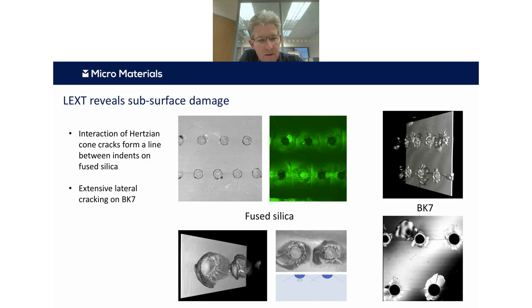So here you can see in the middle there at the top, actually there's a lot more going on in these systems subsurface, and you can see these straight lines, or curved and straight lines, between these impacts that you're not seeing at the surface. One of the nice things is that because these samples are optically transparent, you can look through the samples, and the LEXT imaging allows you to rotate these things and build up this pattern of what's going on subsurface.